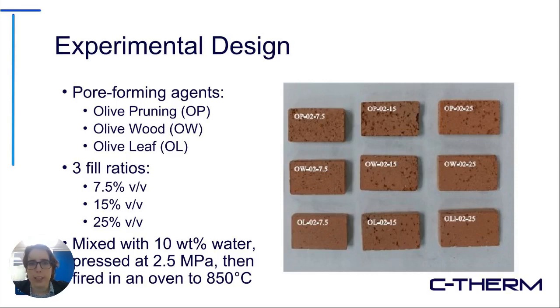3 pore forming agents were used, and the first 2 letters of the sample code indicate which pore forming agent was used. The last 2 to 3 digits of the sample code indicated on the brick indicate the fill ratio. So the fill ratio was varied between 7.5% by volume up to 25% by volume.